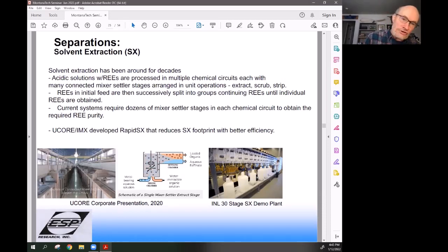In terms of separations, let's talk about the solvent extraction first, or SX. It's been around for decades. We take these acidic solutions where we dissolve the material out of the ore or out of the concentrate, and then we use multiple mixer settlers to get these things to happen. I'd say the extreme for this is probably at the California site, where they dissolve the materials and then run these 500 to 700 gallon tanks where they add the solvent, which is kerosene, with the extractant dissolved in the kerosene, and then you take the metals dissolved in the aqueous acidic solutions and mix them together. And the metals are pulled from the aqueous solution into the organic phase.